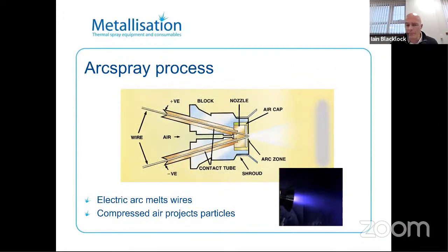So onto the arc spray process, we bring two wires together. This is the electrical system: one we apply a positive charge and one we apply a negative charge. And we bring those two wires together at the front of the pistol. They're driven together and when they touch, it creates an electrical arc which melts the wire. And then the compressed air, again, atomizes it and propels it onto the substrate. For zinc, you get this lovely blue hue on the front of the pistol.